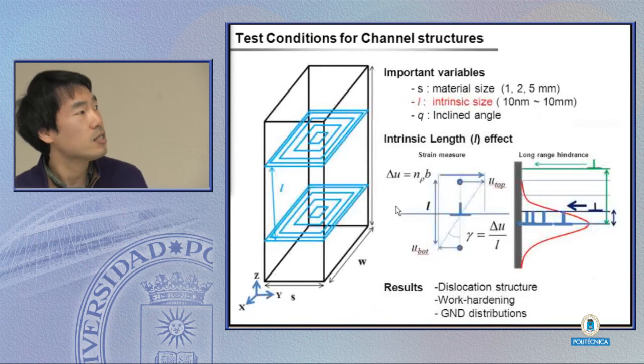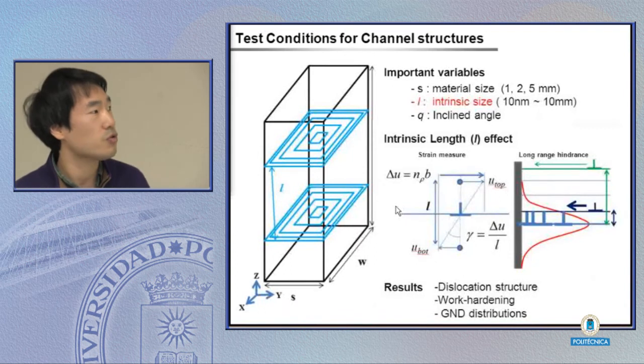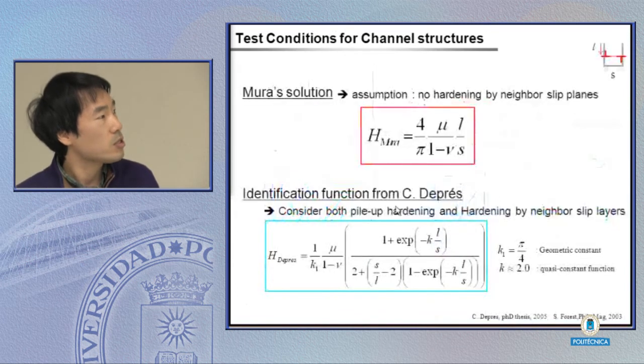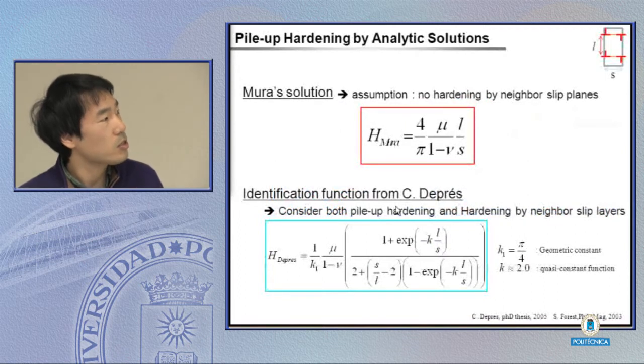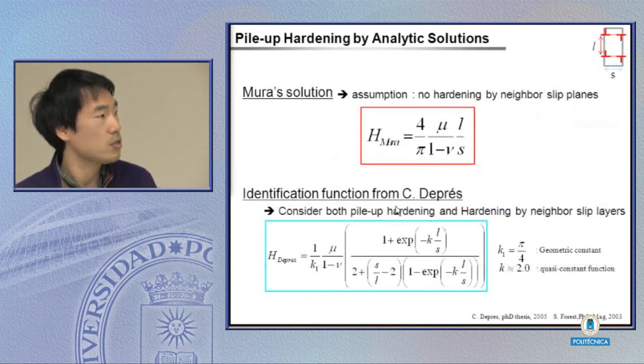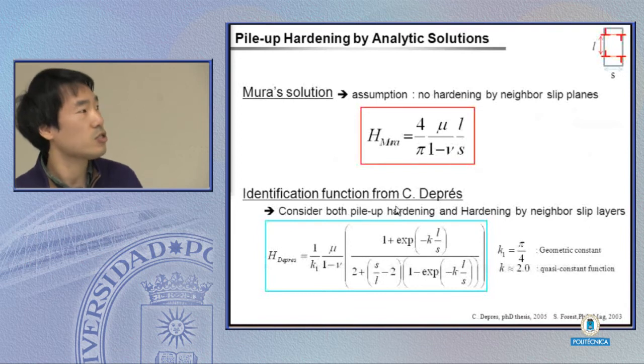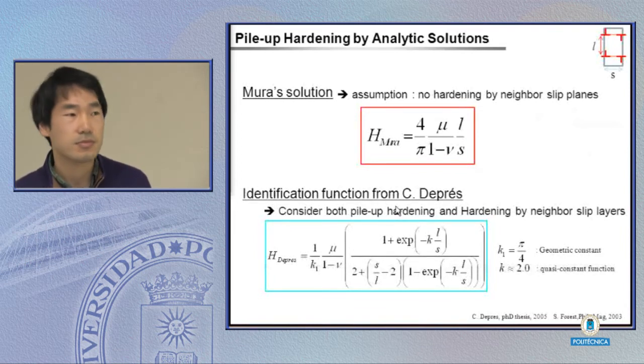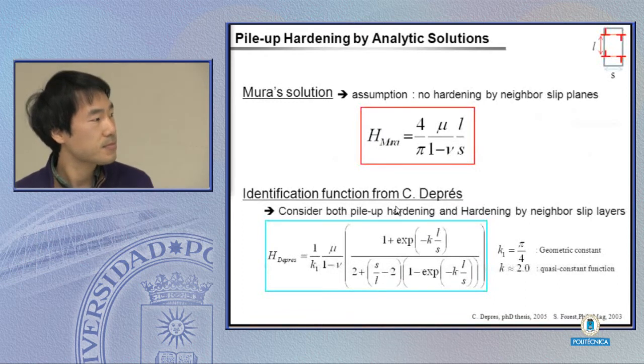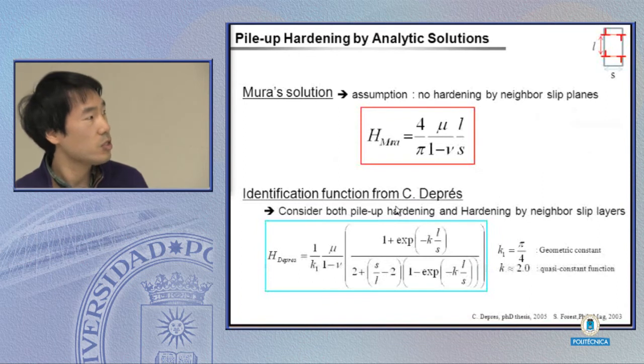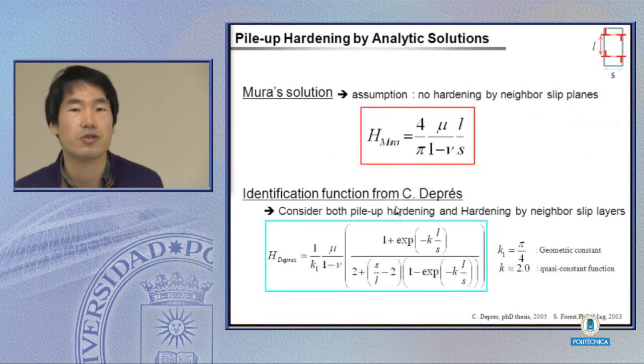The intrinsic size is very important because of two reasons. One is it makes the strain measured directly, and it also affects the long range hindrance like this. And then using this simulation situation, we will have the dislocation structures, work hardening, and GND distributions.